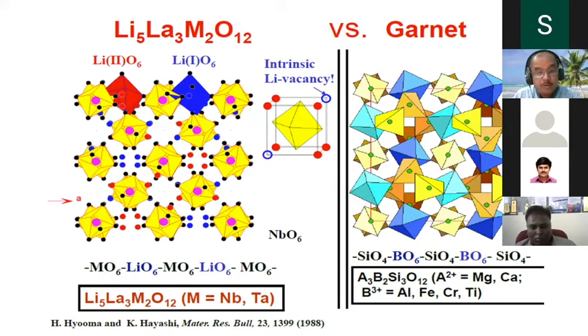Before moving to lithium garnets, let us look at the ideal garnets and the lithium garnets. That is the purpose of the structural chemistry proposed based on powder X-ray diffraction. If you look at the ideal garnets, you have the perfect tetrahedral coordination. But if you come back to the lithium garnets, lithium is occupying two distorted octahedral coordinations. In the ideal garnet it's completely occupied, but here at least one lithium site is not completely occupied. You are having some vacancies.